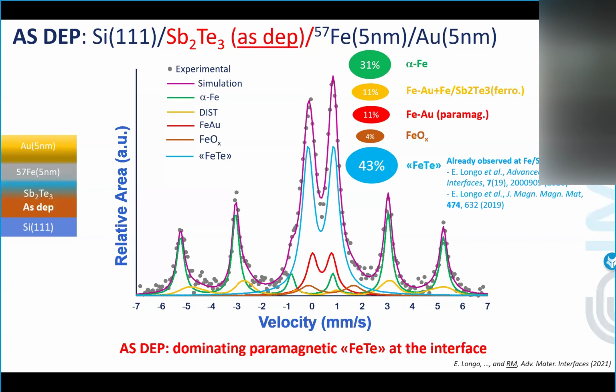When we move, we identified this also. We had a few papers about that, 2-3 papers discussing this. We identified this doublet, central doublet, with the formation of a sort of intermetallic iron tellurium, also combining with many other techniques like TOF-SIMS, XRR, because this is always necessary, as Jean-Marc very nicely stressed this morning, in order to have a final picture. So details are all in these papers, and we are sure that at the interface here, there is this formation of iron tellurium.